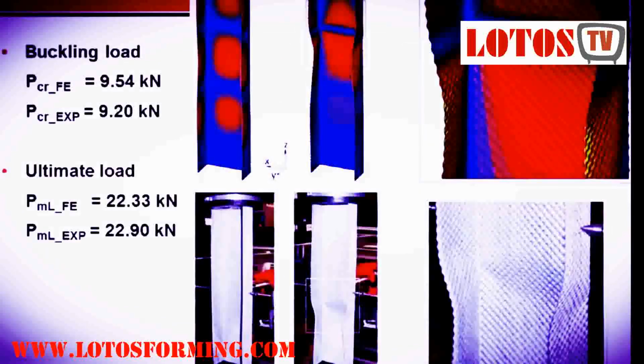And this is the fail mode, and we compare this fail mode with the experimental result. As you can see in the picture on the right, the top is the simulation result and the bottom is the experimental result. You can see the buckling mode compares well with the buckling mode in the experiment, and the fail mode here also compares very well with the fail mode that occurred in the real samples.